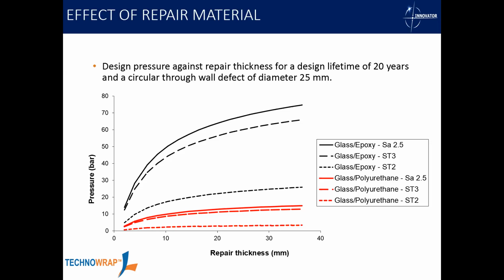Now, Shona did mention earlier that we have a temporary repair offering, polyurethane. The quick fix, it's not an engineered solution, but these red lines just show where that fits in terms of adhesion compared to our engineered solutions. You can see even for a grit blasted surface profile, with our temporary repair solution, you're lucky if you get 10 bar for the same repair thickness. And hand preparation is hardly even worth thinking about. It's maybe one or 2 bar of pressure retention there.